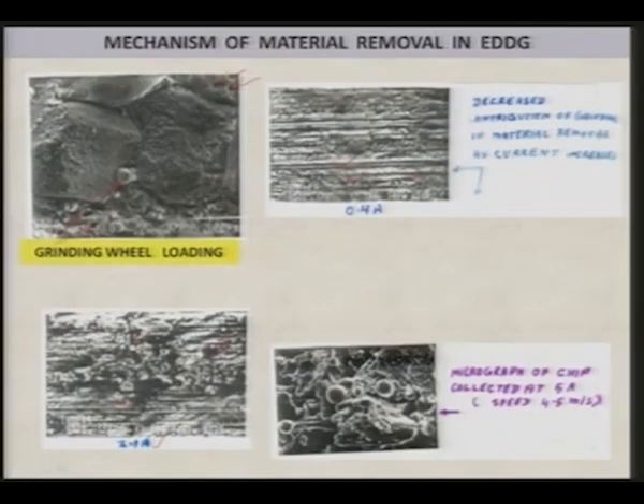You can clearly see the ball-like things or globules, which clearly indicate, at 5 ampere current and 4.5 meter per second speed, that the mechanism of material removal is melting as well as grinding. Melting evidence is very clearly visible here, and this work has been taken from the paper published by Koshi, Jain and G.K. Lal.